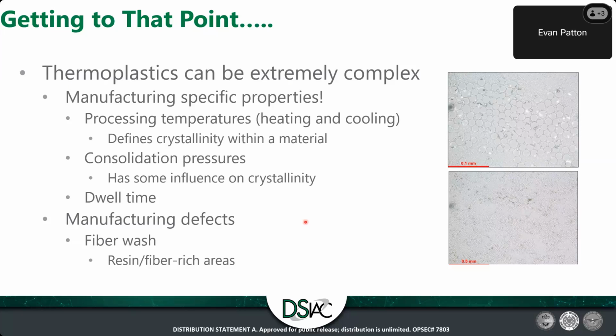And as a subset of the manufacturing specific properties, we have defects such as fiber wash. Fiber wash occurs in a sample when, say, you have a mold with a little bit of air void from maybe a tolerancing issue or things like that. When the resin, in this case thermoplastic, is molten, it'll want to flow and fill that void, and it'll actually drag some of those fibers with it, causing resin-rich and fiber-rich areas, as well as off-axis fibers. So it's really important to have a manufacturing specific mechanical characterization so you can then feed your finite element models a more accurate representation of the material you're actually using.